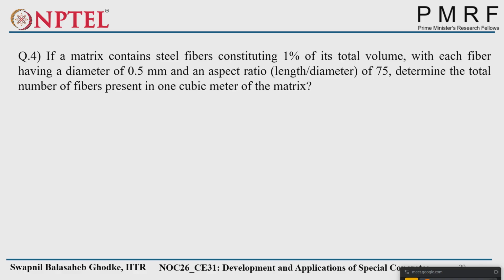1% means 0.01, right? Total volume, because every time we'll go with 1 meter cube only. So diameter of each fiber is 0.5 mm. Aspect ratio is 75. Aspect ratio means L by D. First of all, write down all the parameters we have been given. We have given total volume. The matrix contains steel fibers constituting 1% of total volume, so Vf is given, 0.01. Diameter is 0.5 mm. L by D is 75. So we have D, and we have L by D also, so we can calculate the length. So what will be the length?